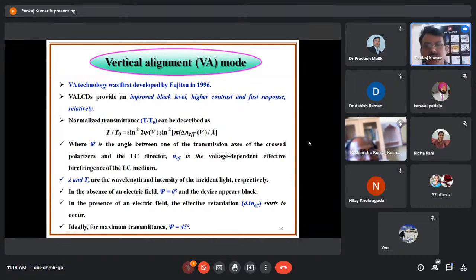In absence of the electric field, psi is 0, and the device appears black. T by T naught will be 0 when we put psi as 0. In the presence of the electric field, the effective retardation, that is d delta n effective, will start to occur, and we get the maximum transmittance when psi is 45 degrees. It means that when the angle psi between the transmission axis of the crossed polarizer and the liquid crystal director is such that the aligned liquid crystal molecules are parallel to one of the axes of the analyzer or polarizer, then psi will be 0 and it will appear dark black.